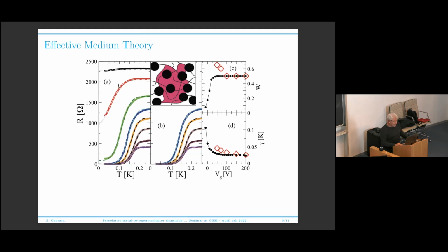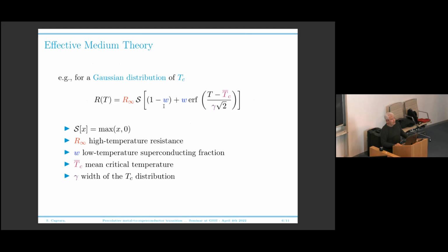So the resistivity in your sample as a function of the temperature is the resistivity at high temperature, the one you measure in the metallic phase, times this function, which is nothing but the maximum between the argument and zero. And this is 1 minus W, which is the metallic fraction, times the resistance at high temperature, plus W, the superconducting fraction, times this error function, whose width is related to the width of the distribution of critical temperatures. With this function, which is an explicit analytical solution, you can fit the data. And this is what we did here. So the broken lines are the fits obtained with this solution within the effective medium theory.